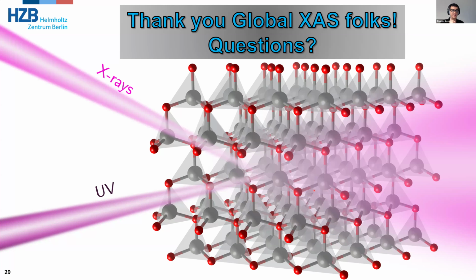Now, the big difference is that here we are talking about excitation densities that will probably be much smaller than the ones that we see in these pump probe experiments. But I suspect that if you measure for a sufficiently long time, this should still be possible. So that's for just the static part. Then if you're talking about core exciton screening at, let's say, even other edges, I think it's quite well established at the M edge of several semiconductors, although people have not called this core exciton screening. I think they give it a different name. So I was more wondering if you'd expect to see core excitons screening other core excitons. So no optical excitation, no bandgap excitation.